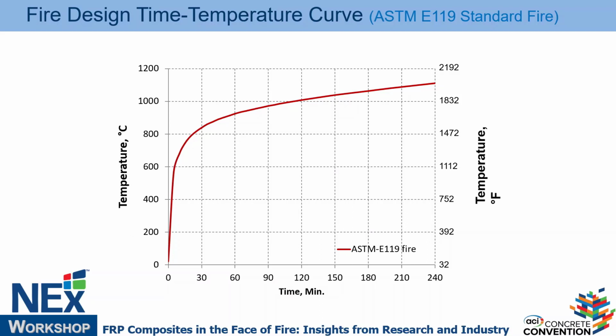There's the ISO curve in Europe that's been used, very similar to this. Canada uses a similar curve. And I think someone this morning showed a presentation. This is considered relatively on the conservative side. It's almost like an envelope, right? So that's why when we do E119, it's very unlikely to get exceeded. It can be exceeded if you have too much fuel. It's not absolutely conservative, but it's conservative most of the time for typical structures.